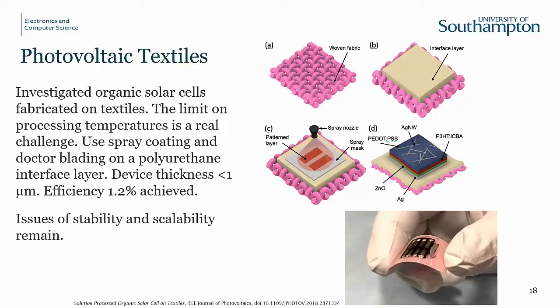And obviously there are many examples of plastic, flexible photovoltaic devices out there commercially available. So essentially we took these commercially available materials and we tried to apply them to a textile, very naively thinking it would be easy. And it really, really wasn't. Effectively, this device thickness is less than a micron, and the surface roughness of the typical textile is over 100 microns. It's fluffy, it's porous, etc. So you definitely have to use this interface layer to smooth the textile as much as you can.